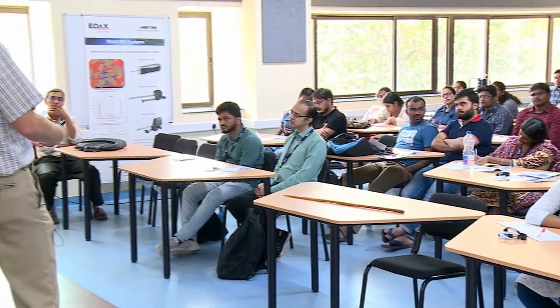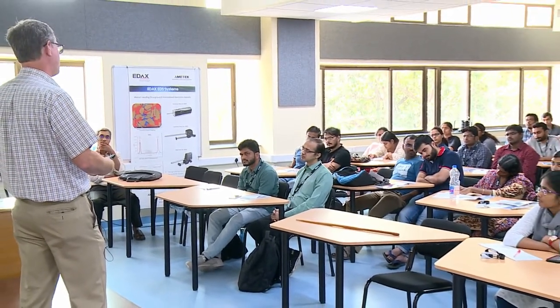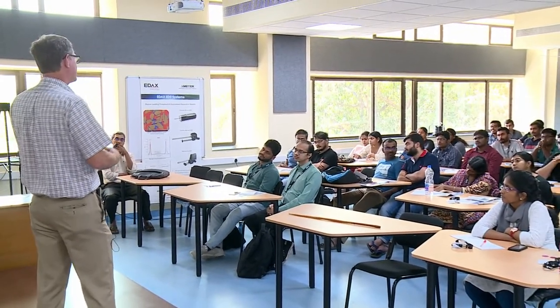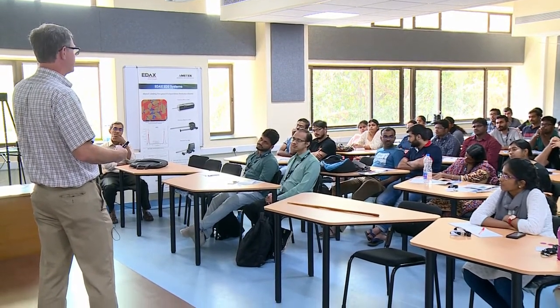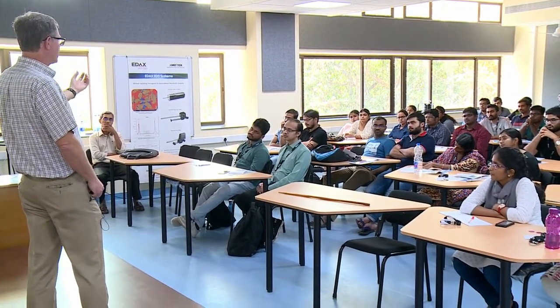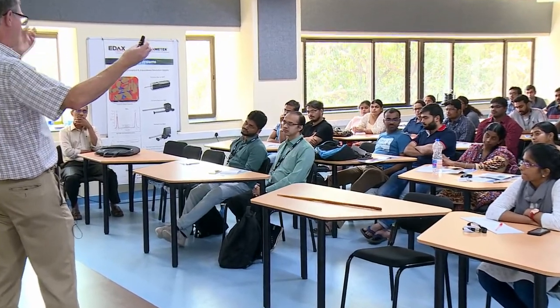You have a better chance. Let's say you set up your Hough wrong, and all you saved was the Hough peaks. Well, that doesn't really help you. Whereas if you save the raw data, and especially now more and more people are saving the patterns and not indexing because they're not even going to do the background correction. They're going to do the background correction afterwards too, because if you have two phases and one's got very weak signal and one's got very strong signal, you're going to want different backgrounds for those two. And so in that case, saving the raw patterns before background correction is actually a good idea. Good question though. Thank you.